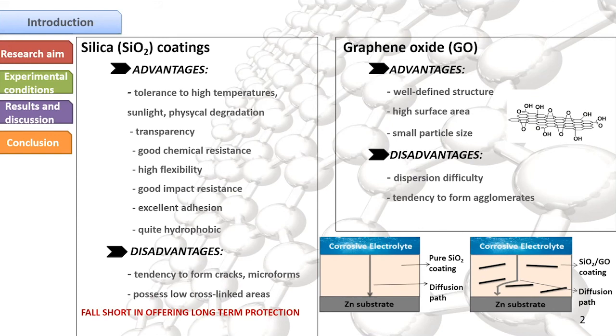But despite the fact that silane films are quite hydrophobic, they fall short in offering long-term protection because of their tendency to form cracks, micropores, and low cross-linked areas. Graphene oxide is thought to improve the corrosion resistance of polymeric coatings by lengthening the electrolyte pathway and decreasing the porosity of the coatings, which is illustrated here. This is due to their well-defined structure, high surface area, and small particle size.